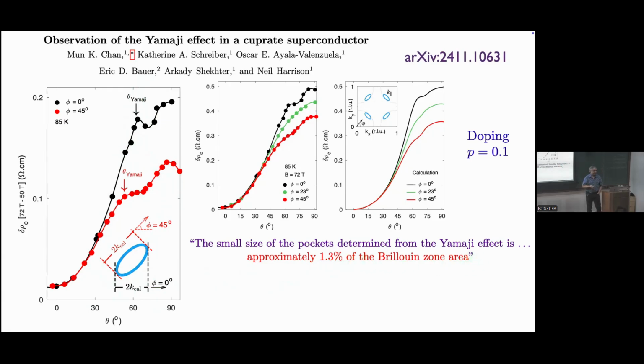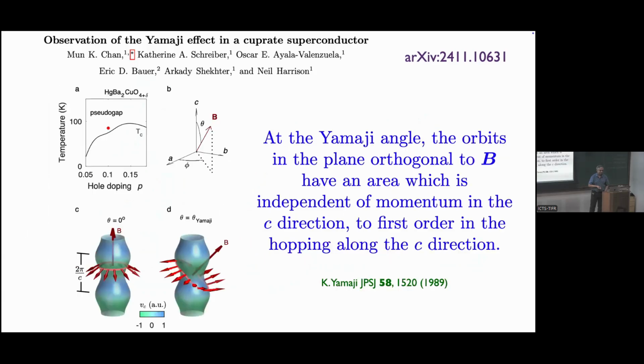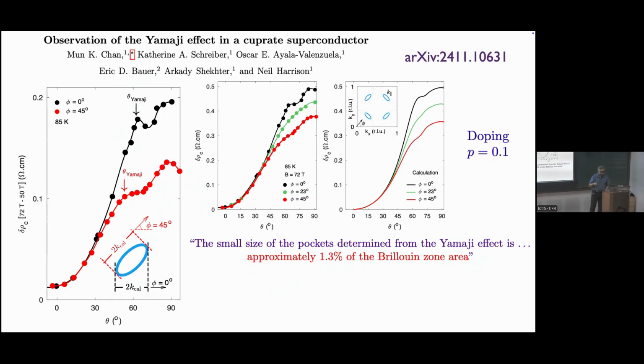So this is the first clear measurement of the Fermi surface size in the pseudogap, at this doping and at this temperature. You have a measurement of the Yamaji angle and hence the size of the Fermi surface. That's quite exciting because now there's a number. And now I'm going to tell you about a theory going back 20 years where we predicted that number. So that's what I'm going to show you now.